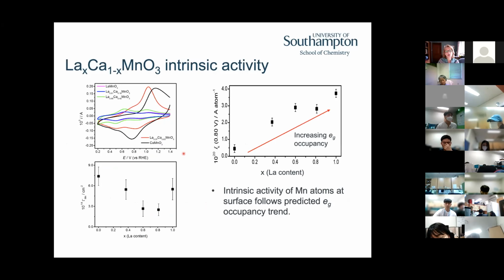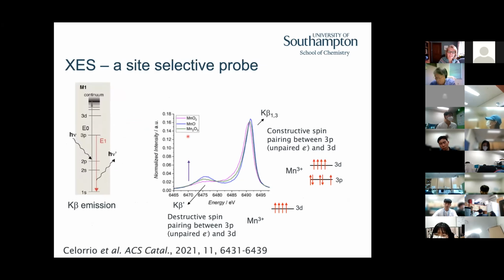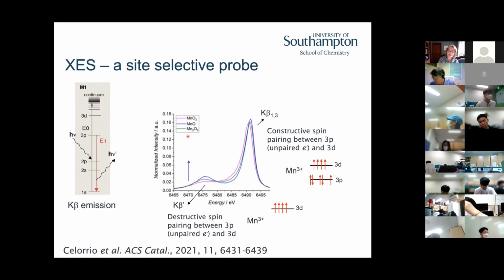We then looked at the intrinsic activity by thinking about the amount of the manganese ions that are active, right? And that made more sense, right? So it's the fraction of the ions on the surface of the particle that allow you to understand it in more detail. But really, I blitzed through that because I want to talk about this really new method that we can use to look at these complex samples with X-ray emission spectroscopy.